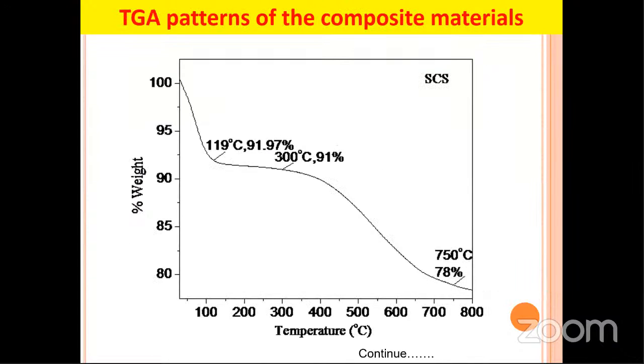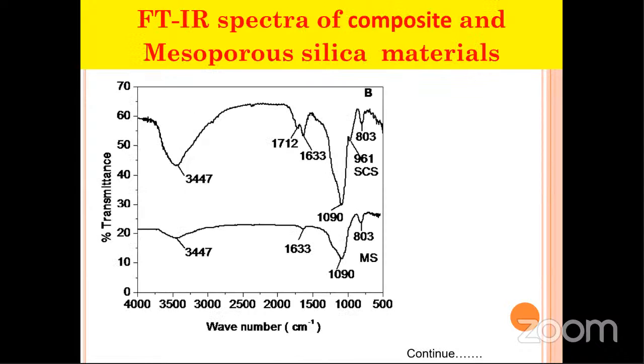The stability of the material was confirmed by TGA, DTA. You can see that up to 300 degrees centigrade, the material is stable. The high moisture content of this material is due to the presence of more hydrophilic groups in this material, like OH, SO3H, and COH groups. The presence of various functional groups was confirmed by FTIR analysis. You can see that the peaks related to SO3H and COH group containing peaks are visible in SCS material, but in MS material these disappear, because after calcination the carbon moiety is removed. So it confirms the total removal of carbon from silica.